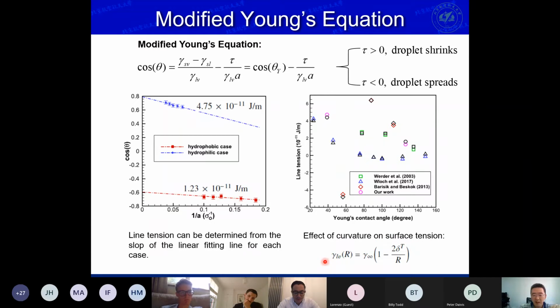So we can use this equation to substitute into the modified Young's equation, and we can get a modified line tension. If we do this, we can modify the line tension a little bit, as shown in this figure. Where the symbols shown in black color are the modified line tension. As you can see, the modified line tension is changed a little bit, but not too much. So the data are still scattered. So we believe that there are more critical reasons that caused the scattering of the data.